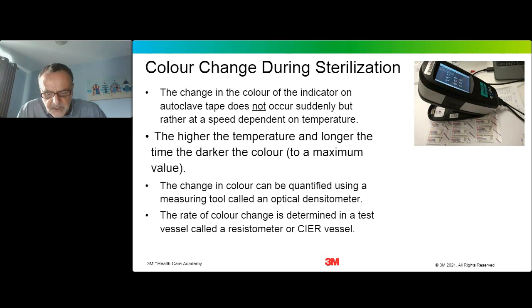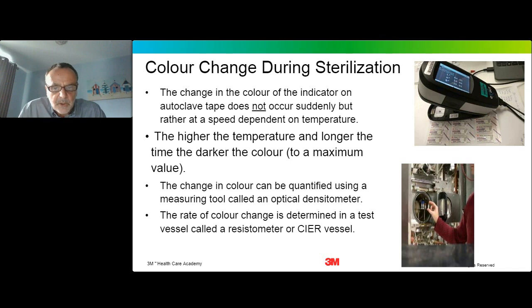The colour change will actually occur gradually and at a speed which is dependent on the temperature of exposure. So the higher the temperature, the quicker the ink changes to its final colour. But that colour change is not instantaneous. I often got questions from customers asking, well, at what temperature does the ink change colour? Well, it doesn't. It changes colour at a speed related to temperature, and the higher the temperature, the quicker the colour change. But it should be noted that the ink will eventually reach an equilibrium plateau colour, and this is called its endpoint. So when testing tapes, the colour change is normally established using a piece of equipment called a resistometer.